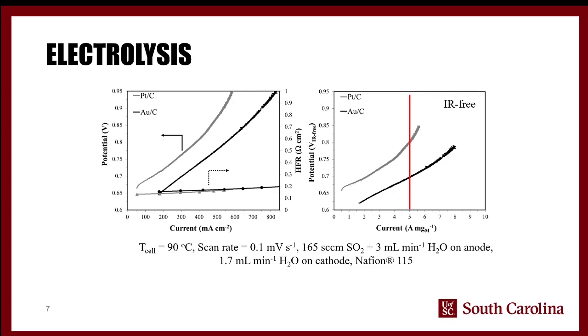And so you have to scan it slowly enough that you can allow the system to equilibrate, and scanning at 0.1 millivolts per second achieves that without forcing you to, for instance, do several individual points and tally the data up yourself.